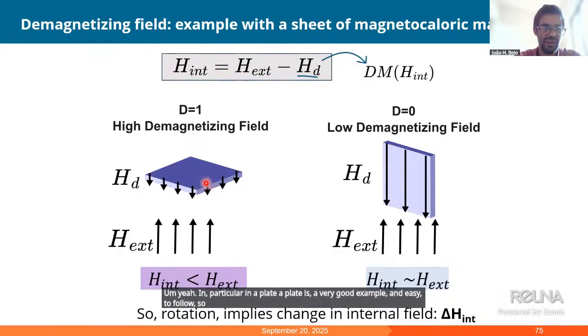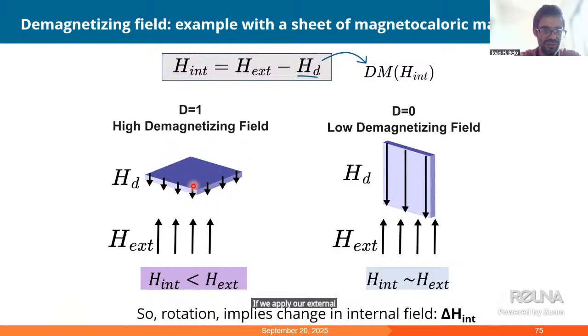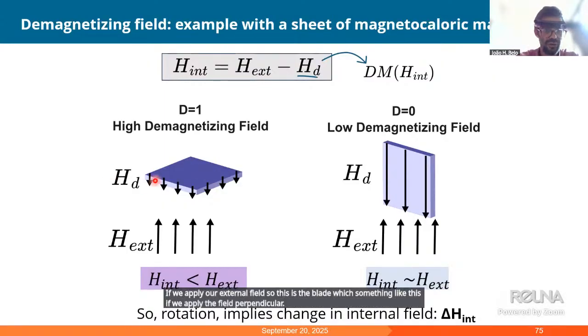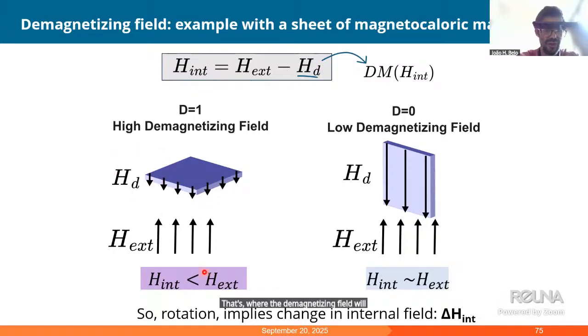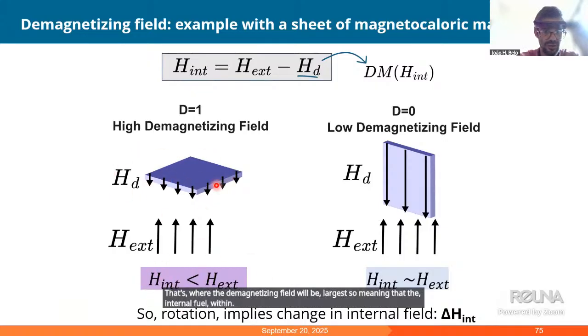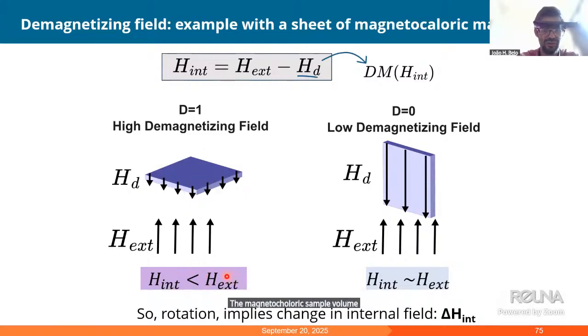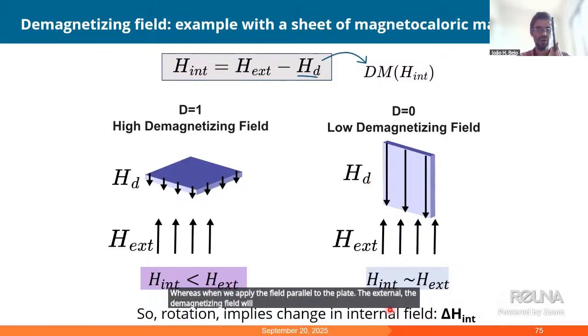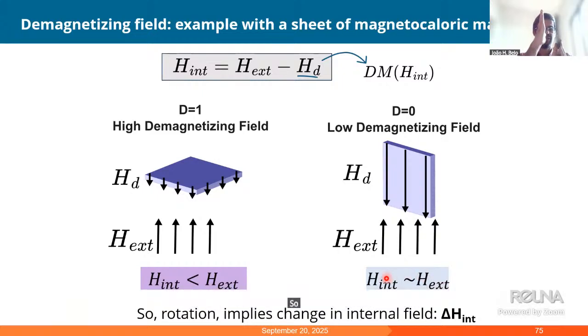So in a plate, if we apply our external field, so this is the plate, something like this. If we apply the field perpendicular, that's where the demagnetizing field will be largest. So meaning that the internal field within the magnetocaloric sample volume will be smaller than the external field. Whereas when we apply the field parallel to the plate, the demagnetizing field will be very small, meaning that the internal field will be roughly the same as the external field. So rotating from one position to the other implies a change in the internal field, which is delta H int.